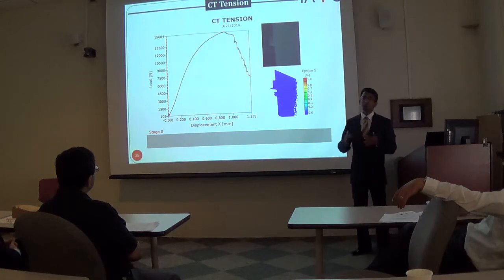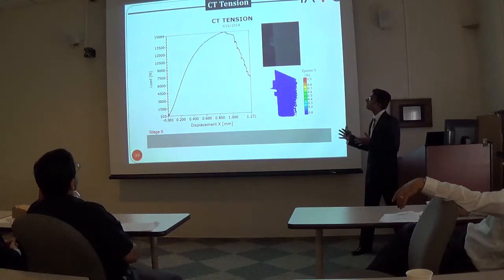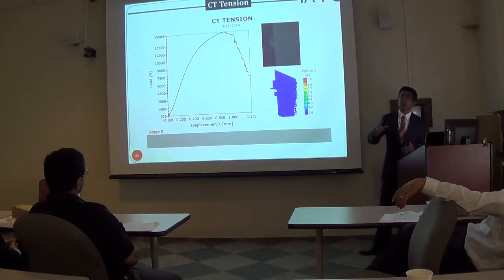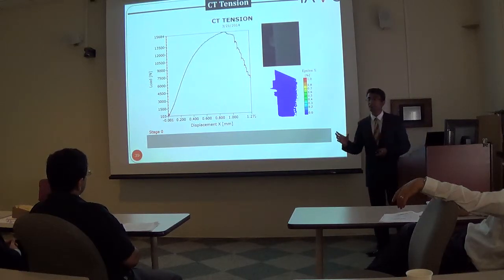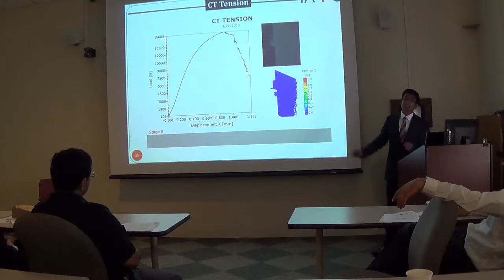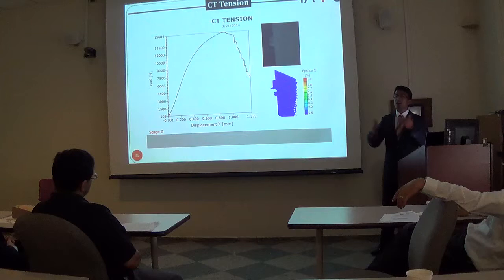So this is the video that was picked up, where it was analyzed using DIC, which shows the full field strain accumulation around the crack tip, but more importantly also tells us exactly when the crack initiates, which can then be utilized to interpret the unknown and large AE signals that are detected in real time. So if I can just go ahead and play the video.